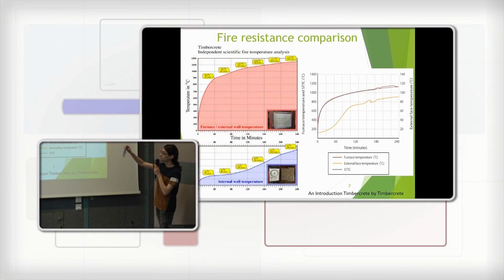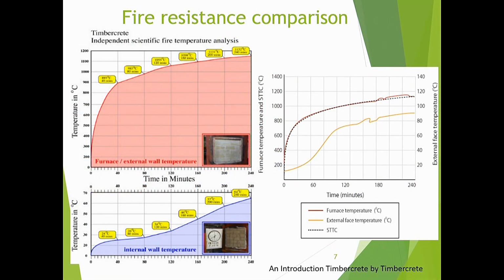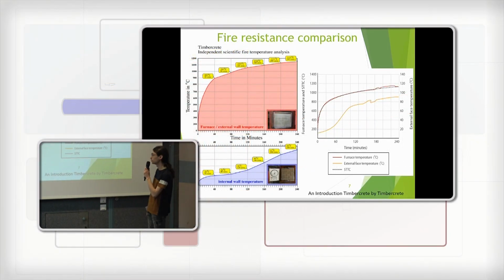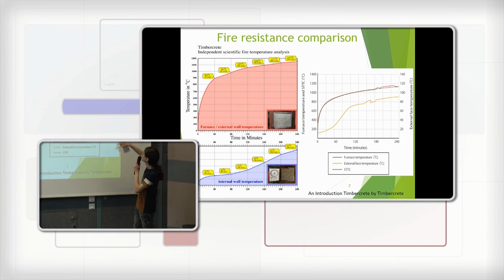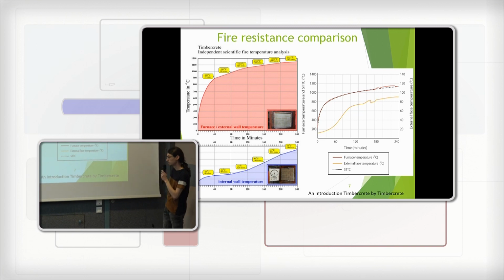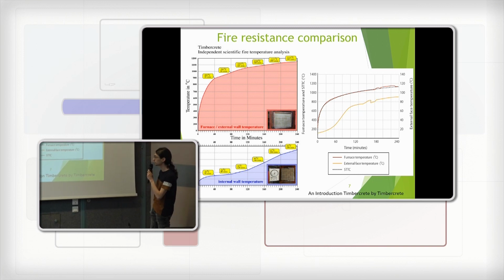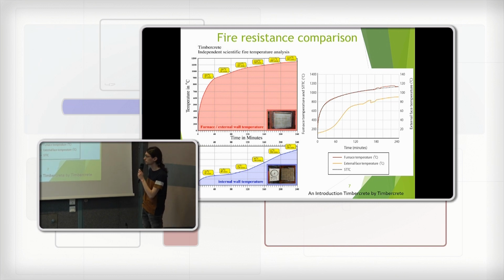Then we obtain the two graphs we have here. On the left we have the graphs for timbercrete, and on the right the graphs for concrete. The furnace will heat up the walls to over 1000 degrees, and we measure the temperature on the other side of the wall for 4 hours. In the end, we can see the temperature of the wall of timbercrete here at 64 degrees, and for concrete at 90 degrees. So we can see with these numbers that timbercrete has a better fire resistance than concrete. But I have to say that concrete also has a very high fire resistance.